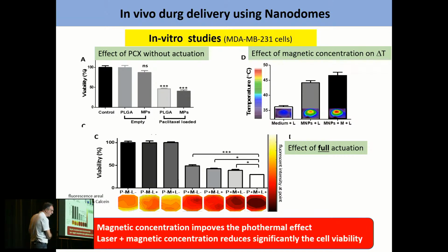And then when we put the particles inside, since they have the drug, there is a decrease in cell viability just because of the effect of the drug. And then when we put the laser on, there is a further decrease in the cell viability. And when we do the magnetic concentration, there is an even further cell viability decrease in the in vitro experiments.